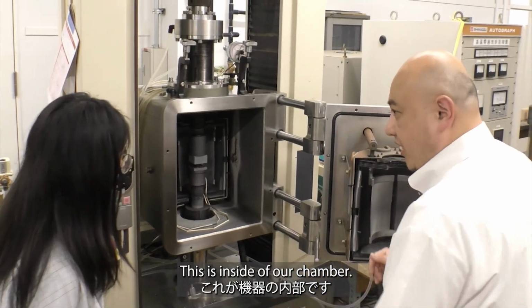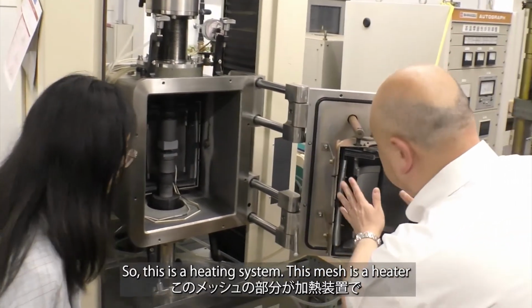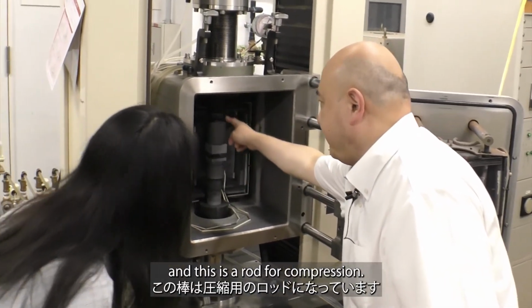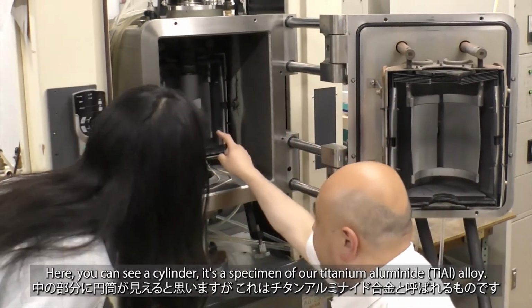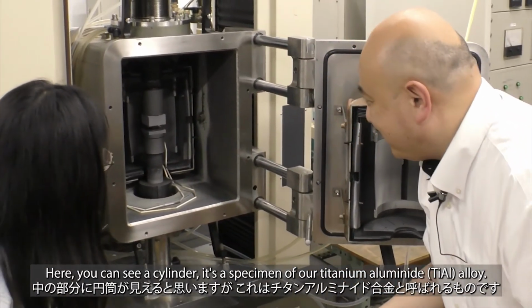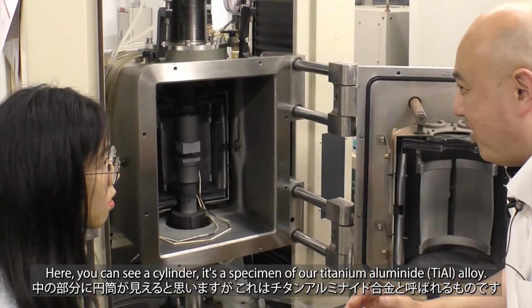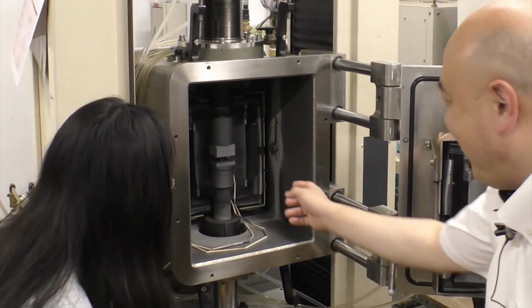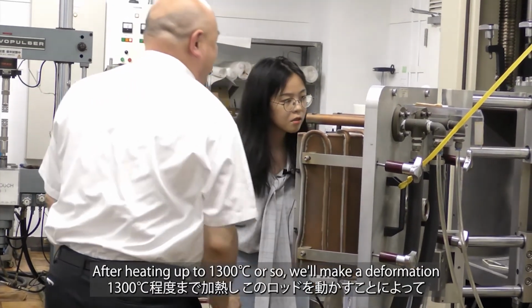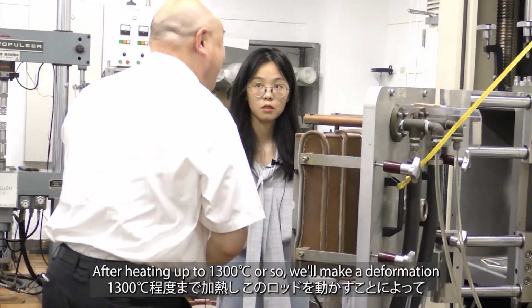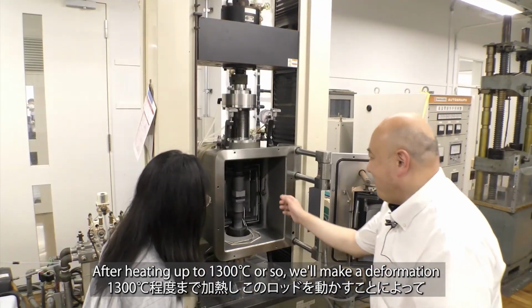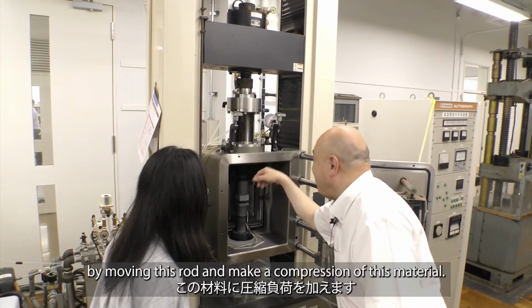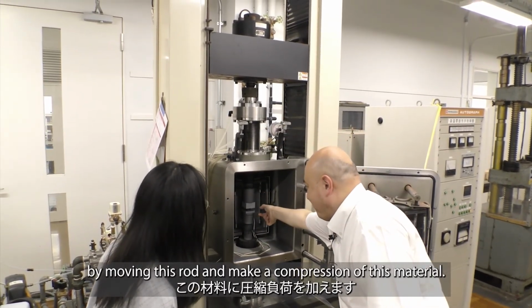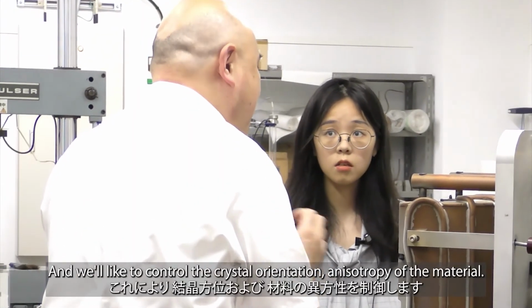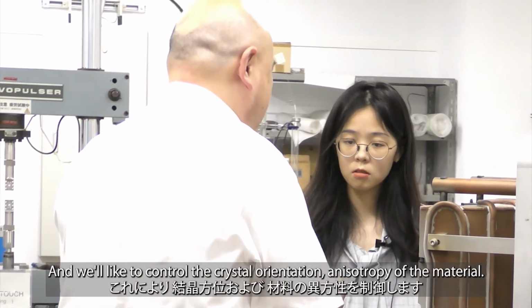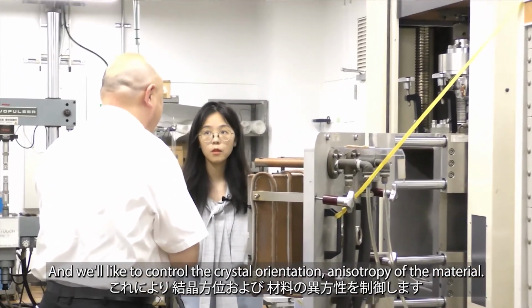I would like to show you the inside of our chamber. This is a heating system. This mesh is the heating system, and this is a rod. And here you can see a cylinder. It's a specimen of our titanium aluminide alloy. After heating up to 1300 degrees C or so, which is very high, we will make a deformation by moving this rod and compressing this material, because we would like to control the crystal orientation, something like anisotropy of the material.